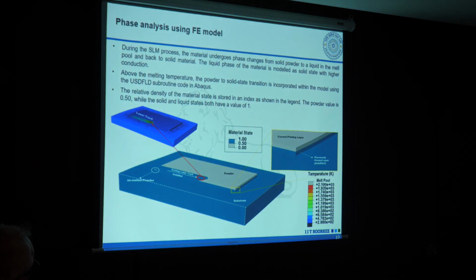Then some phase analysis has also been done. In that case, the material undergoes phase change from solid to liquid pool and back to solid material. And in this case, we have used the user-defined field subroutine code. Basically, this gray one shows your powder, and this shows your liquid, the combination of liquid melt and the solid.